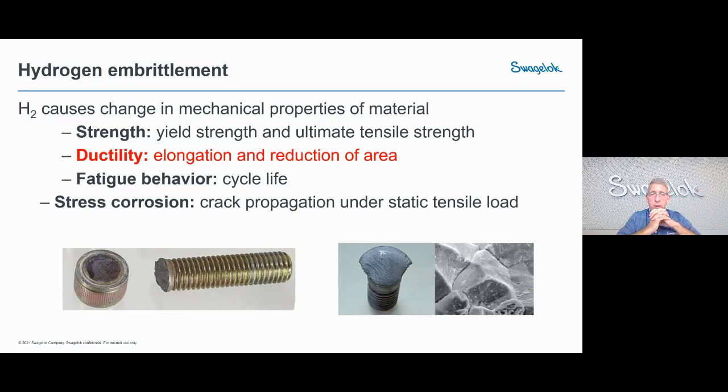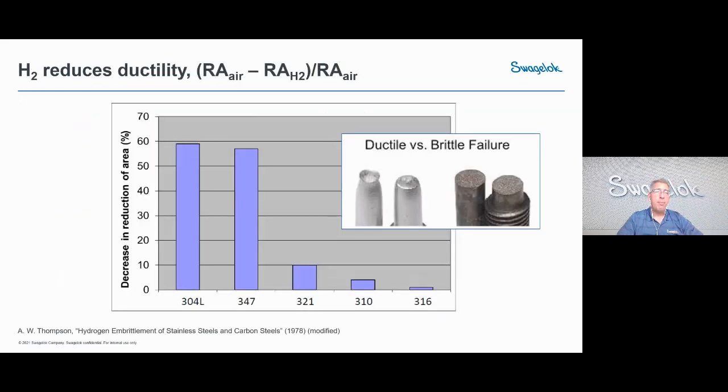They usually occur at locations where there might be a stress concentration, thus indicating that it can be very sensitive when hydrogen gets diffused into materials. But this is certainly something that can be measured in materials through standard mechanical testing processes, where you can measure the overall ductility, or the ability of a material to plastically deform upon being loaded. And so these are ways of categorizing resistance to hydrogen embrittlement, which is shown in the next couple of slides here.